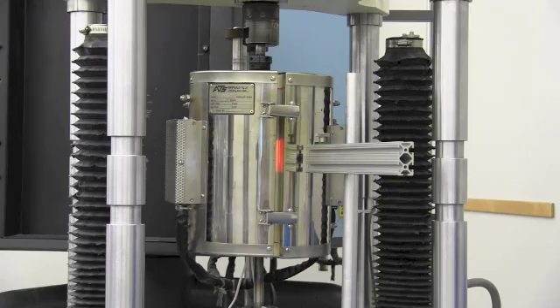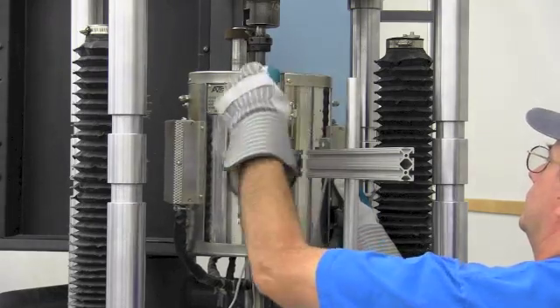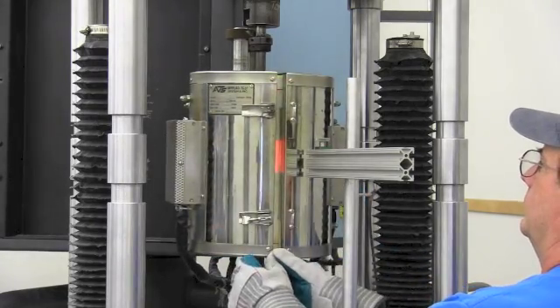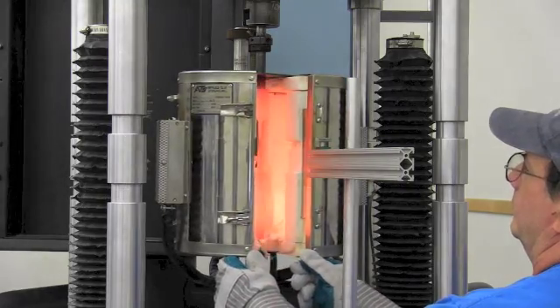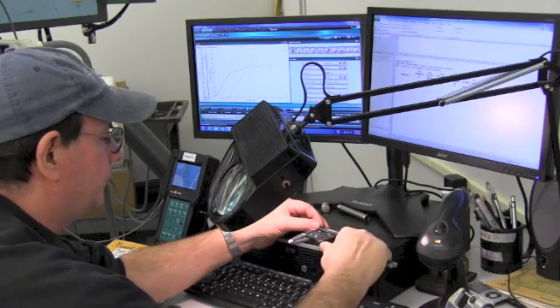Once the specimen breaks the furnace is opened and the specimen is removed and allowed to cool. The specimen is then measured for diameter to calculate reduction of area and for gauge length to calculate elongation.